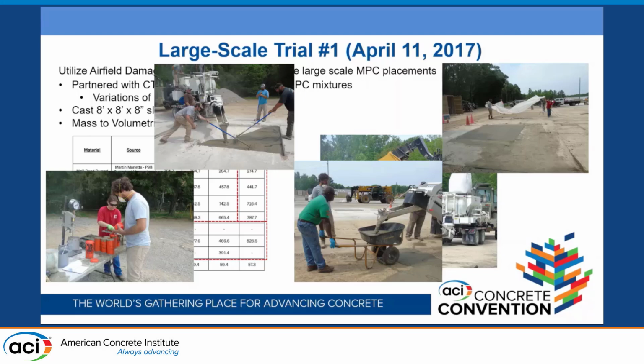And then curing, we ended up sort of having to ground truth curing methods. Because I know that the phosphates can leach out of the system, but we don't want to have any drying shrinkage, we ultimately settled on a curing method that was just covering with plastic. No additional water was added to the surface of the material. So that's one thing that we sort of learned on the fly, but I would like to go back and research some more.